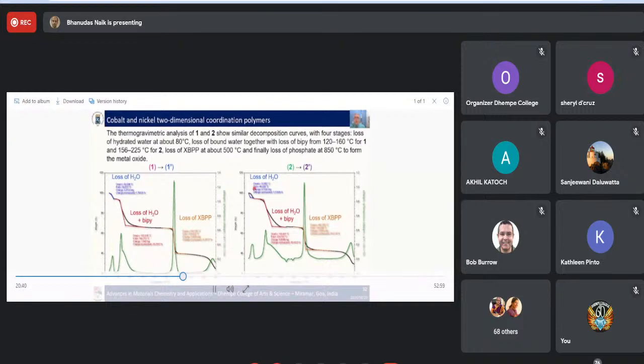And the thermogravimetric analysis of these compounds, this is 1 going into 1' and 2 going to 2' here. You can see that they're heating it up. As you heat up, the first event is basically the same. You have first the loss of the hydrated water, the 2 molecules of water, and then you have loss of the coordinated water and the BP group here. You can see that there's 2 processes happening here. You have a very fine process for the water, and the BP is a longer process. The nickel compound has a very sharp process for the water and a very large process here for the BP group.